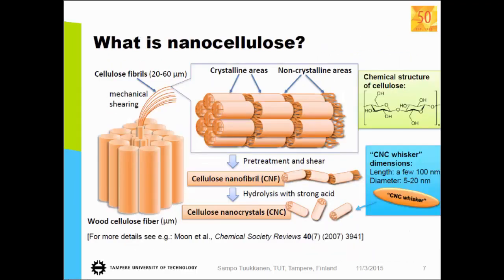And okay, in addition to PVDF, this is something we have only studied for a few months, like 6 months ago. There's some hype around nanocellulose at the moment, at least in Finland, because we have a lot of wood, so we can make a lot of nanocellulose basically. Basically how you do nanocellulose is you take the wood cellulose fiber, then you mechanically shear it. By mechanical shearing, you make it smaller, and in the end you end up at the nanoscale, the fibrils.